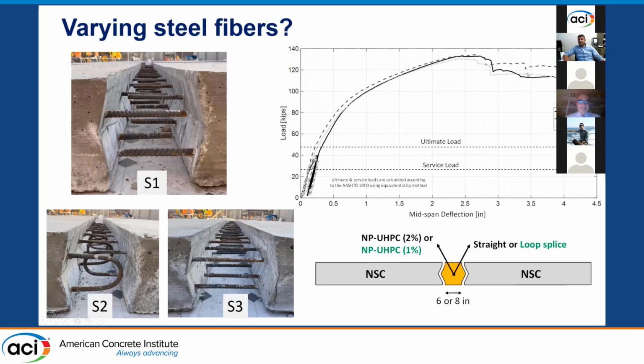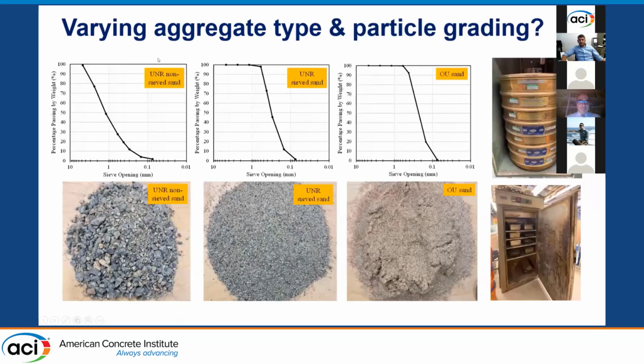And you can see here that the 1% and the 2% concretes have almost identical behavior. So again, I'm usually tying both the material and the structural results together to show the motivation. Why would we characterize the material with 1% steel fiber as well? So that was the steel fiber.